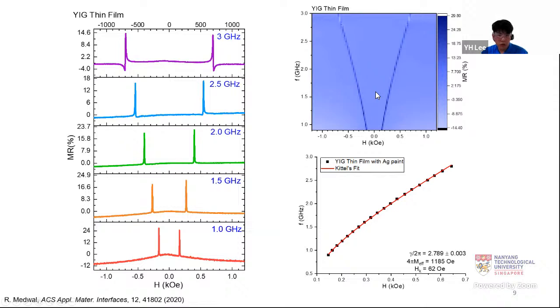Likewise, in the contour plot at the top right-hand corner, the dark shades indeed show the shift. From there, we extract the critical field values using the Lorentzian fitting function. In the bottom right-hand panel, we again fit to the Kittel relation. It gave us 3 important parameters that we are trying to compare. Gamma by 2 pi is 2.789, which is very close to the literature reported value of 2.8 megahertz per oersted.